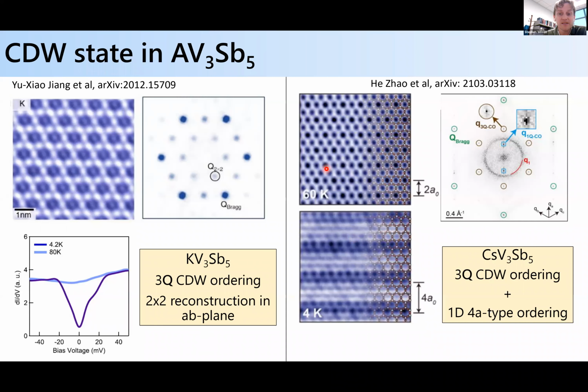Okay, so in a bit more depth, X-ray diffraction measurements that we've done, and this is data collected on the cesium vanadium-3 antimony 5 system. We can actually look and identify the Q vector associated with the charge density wave superlattice, and this Q vector is indicative of a 3-dimensional charge density wave order.